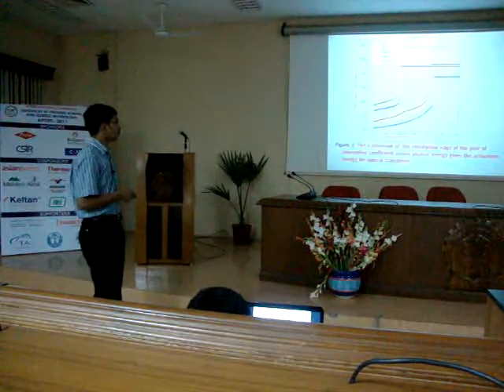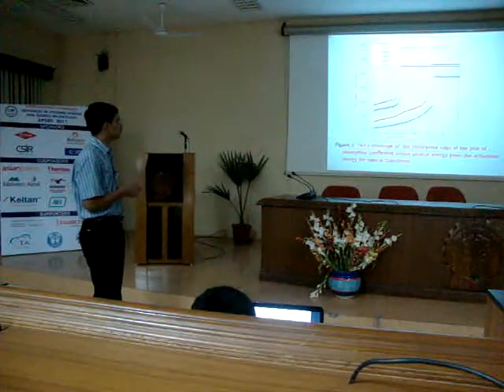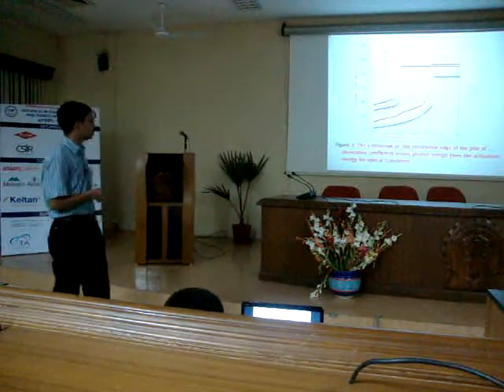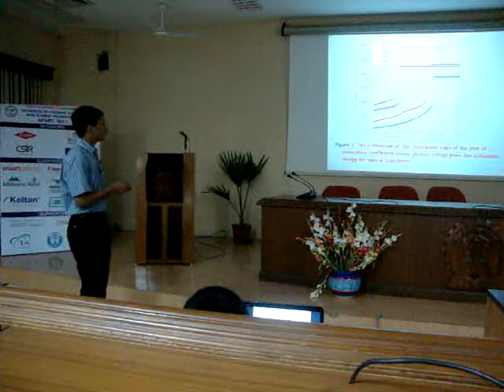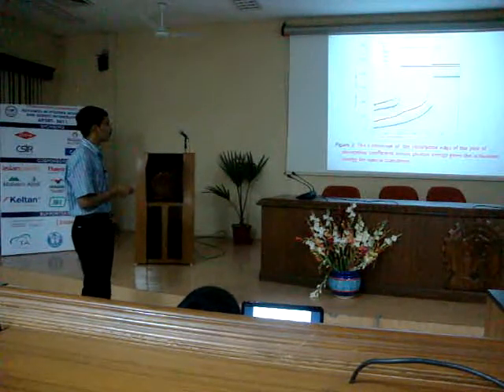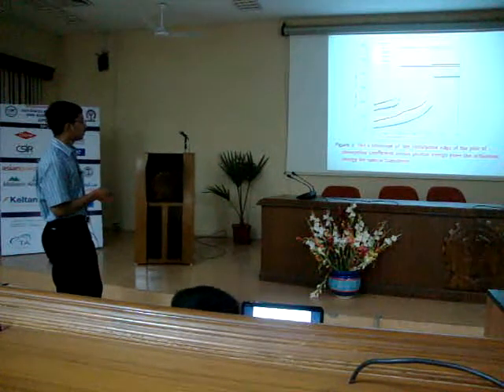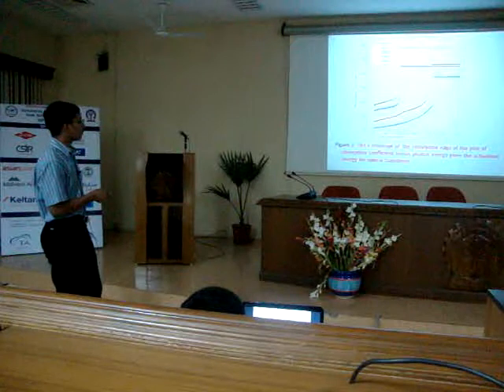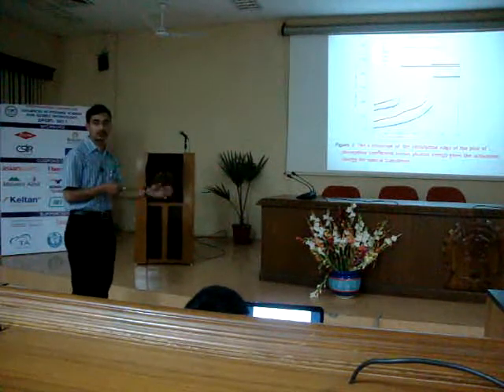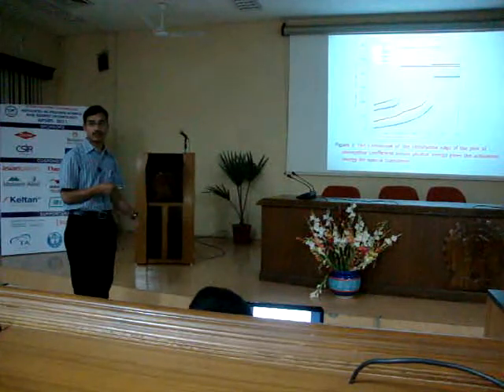The x-intercept of the absorption edge of the plot of absorption coefficient, this is the absorption coefficient versus photon energy, gives the activation energy for optical transitions. So here is the low doping level, so that is the last linear line which you are going to see, is for the lower doping level, and as the doping level increases, the photon energy comes very close. That means this shows that the higher doping levels have good electrical conductivity.